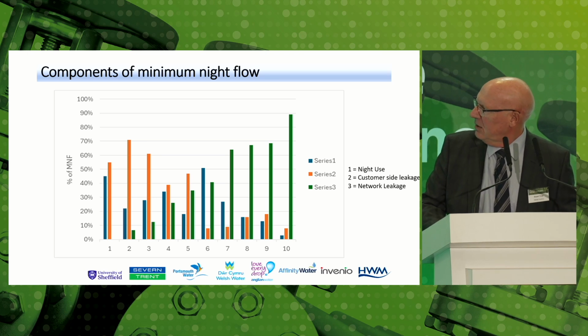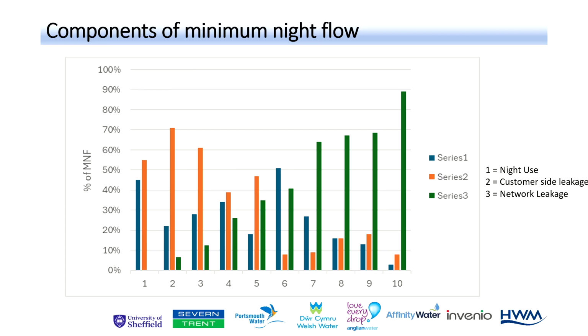So the green bar is the network leakage as a percentage of the minimum night flow, and you can see I've ranked them from least, in other words 0, through to the most. So we've got probably 3 DMAs that have 10% or less of the night flow being leakage on the network, and at the other extreme we have 4 DMAs where more than 60% of the minimum night flow is accounted for by leakage on the network.